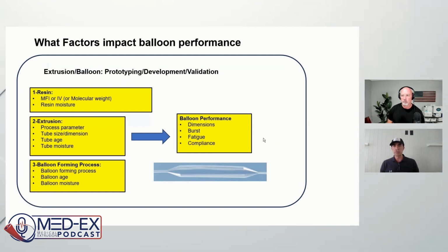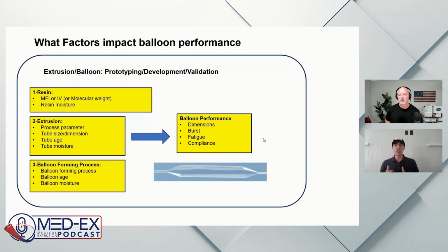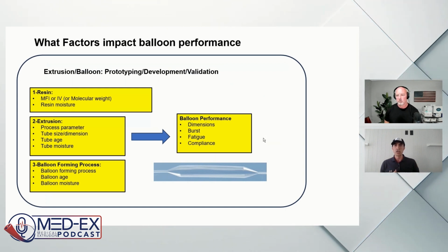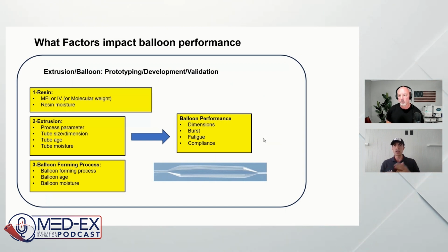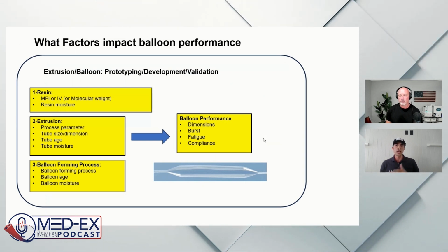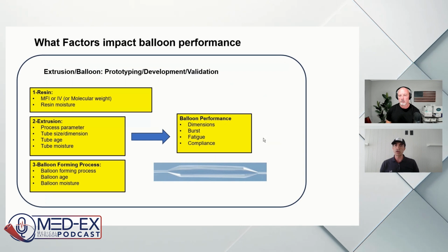Resin moisture is also very important. We know that traditionally moisture would play like a softening agent for the resin, and it could impact the mechanical properties of the final part. Of course, if it gets beyond a limit, it could even disrupt your extrusion, right? Create a lot of bubbles and even stop your extrusion. But to some extent, it would allow you to extrude, and you will see the impact on the final part.